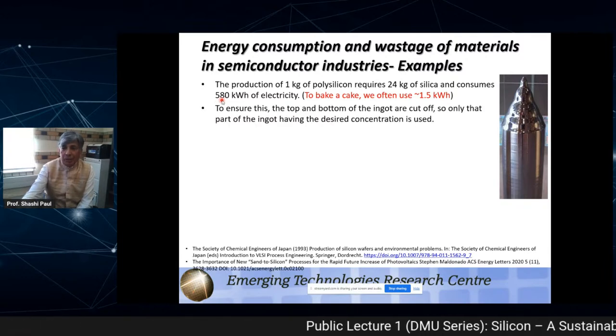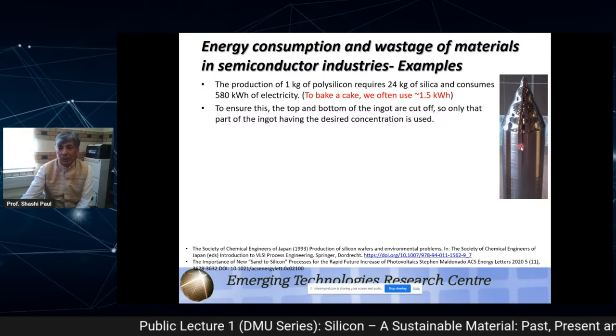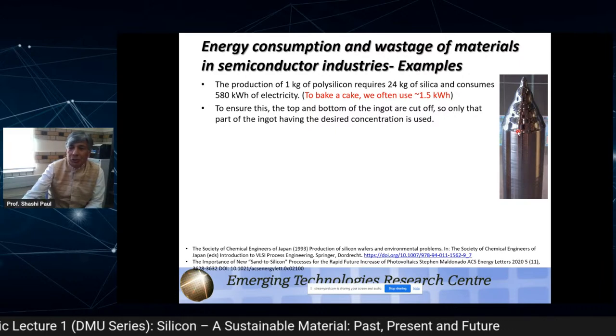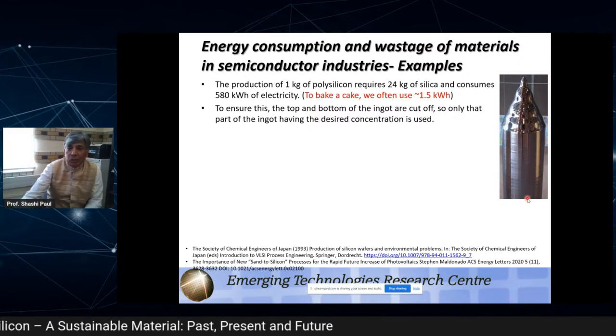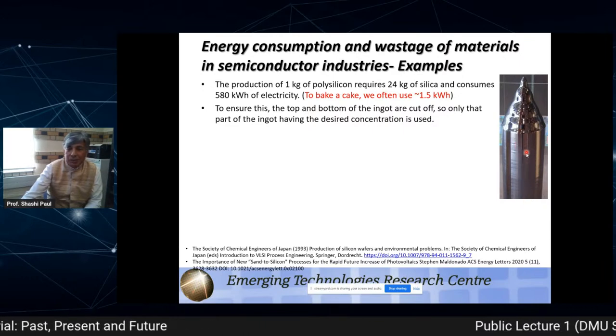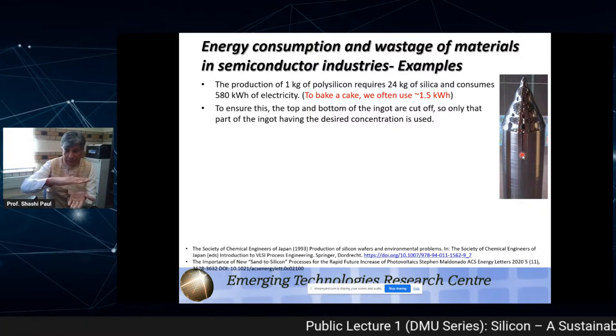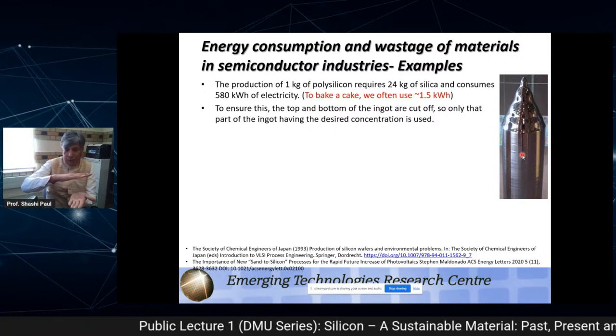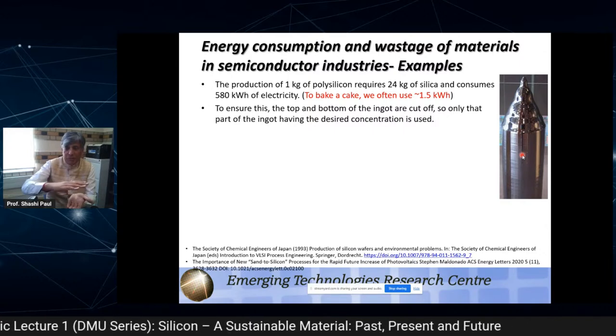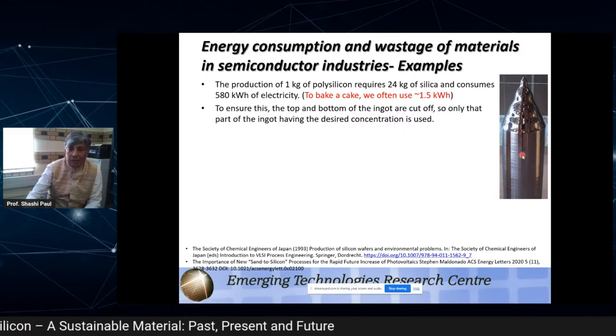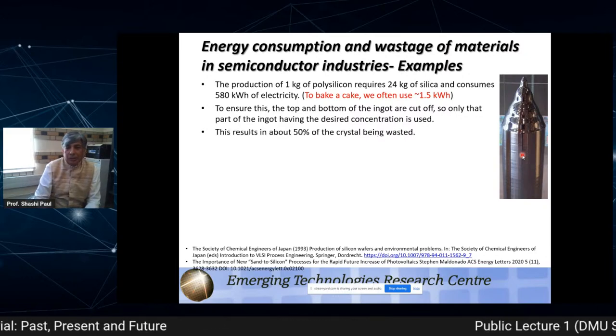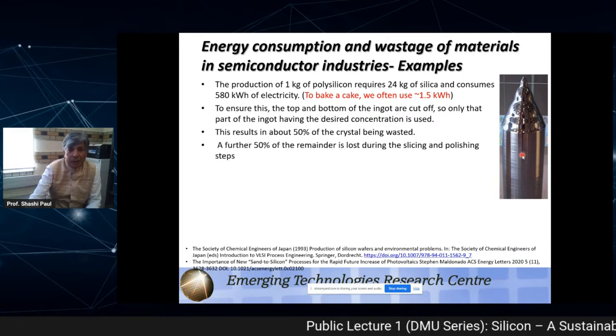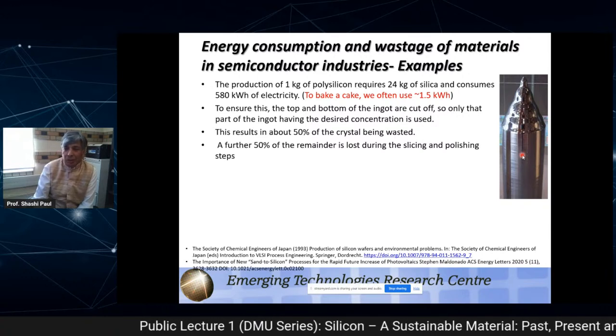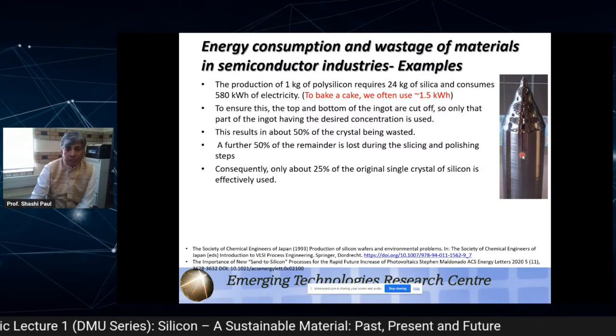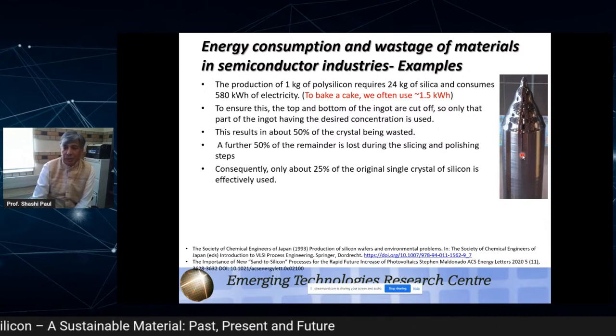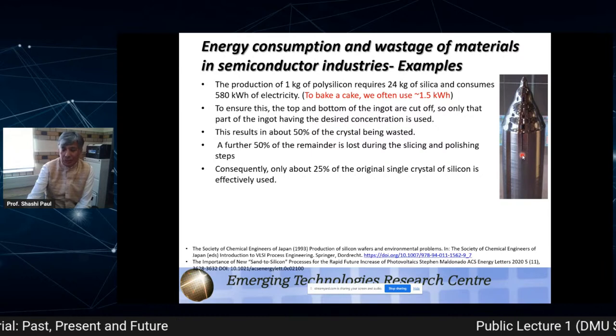And then when we make something like this, it's called an ingot, and then what happens? The top is useless, okay? And the bottom is also useless. And when we slice this one to make silicon wafers, clearly it is a kind of salami cut. When you make slices of these wafers, in the same way you use a diamond cutter, so you lose material again. This results in about 50% of the crystal being wasted. A further 50% of the remainder is lost during slicing and polishing. And consequently, only about 25% of the original single crystal of silicon is effectively used.